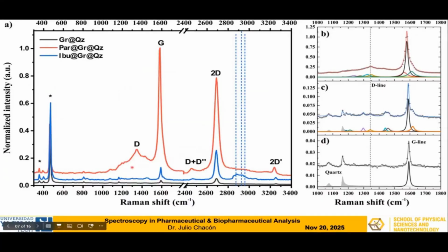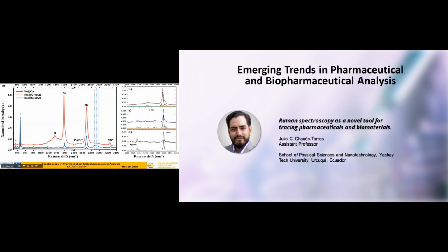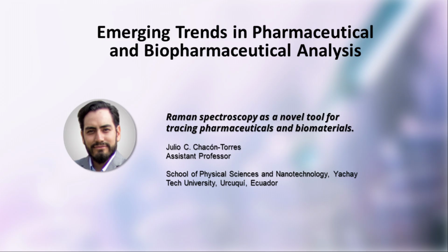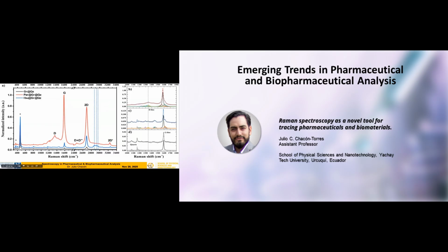Moreover, we notice some additional peaks that appear after we deposited the pharmaceutical molecule on the graphene. For example, those peaks around 3000 and some additional peaks in between the D and the G line and also on the low frequency range below the D line. Those peaks we directly correlated to the molecule that we were depositing.